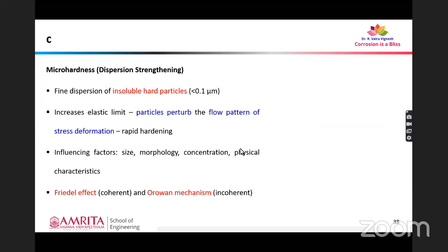When we have a fine dispersion of insoluble hard particles, less than 0.1 micrometer, that will increase the elastic limit, perturb the flow pattern of stress deformation, and lead to rapid hardening. Yes. So there are many factors that influence the dispersion strengthening of materials. First is the size, second is the morphology, third is the concentration, and fourth is the physical characteristics. The dispersion strengthening due to the Friedel effect is very much limited. Why? Because only if we have a coherent precipitate will we have a Friedel effect of dispersion strengthening. And if we have a big hard incoherent precipitate, that relates to the Orowan mechanism.